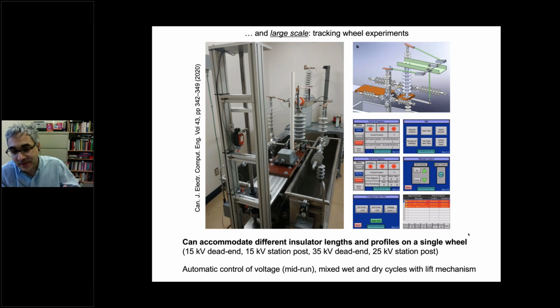And then what happens is this thing rotates, the insulators take their turns being dunked into the tank, then they come out of the tank at the 3 o'clock position, they move into the 12 o'clock position, they're subject to high voltage, they cool down in the 9 o'clock position, and they get dunked again. And furthermore, our design has an automated lift mechanism built in, so we can program wet and dry cycles as they come in and out of the salt solution to look at sunny days and salt exposure days all at the same time.